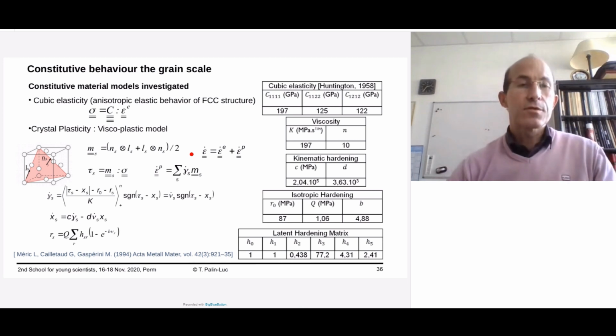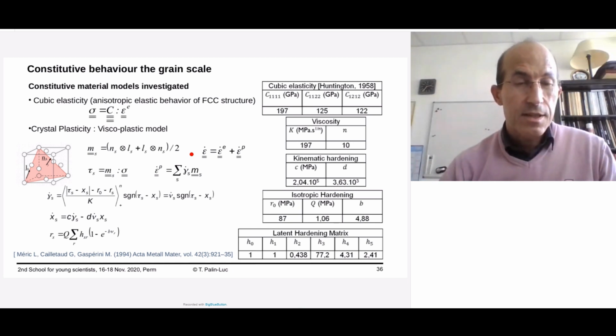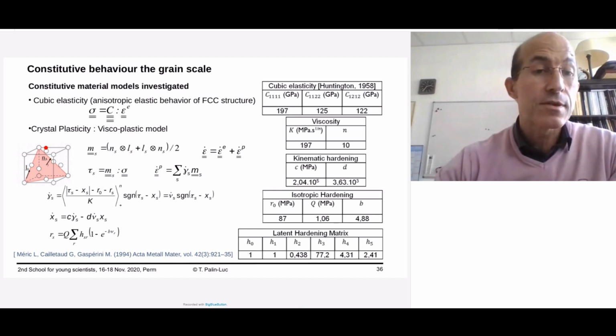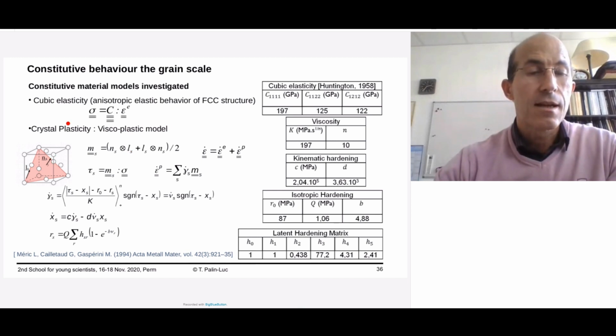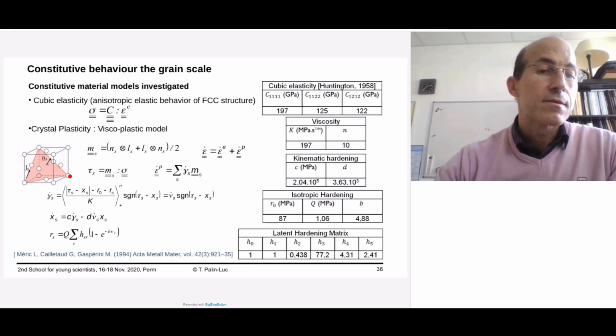The constitutive behavior of the grain in this case is given by different behaviors. There is a cubic elasticity to reproduce the anisotropic grain or crystals. And there is also a crystal plasticity behavior, which is in fact viscoplastic. This is a model written at the grain scale on the different slip systems. So a slip system is for one material plane. You can see here the crystal with a given material plane oriented by its normal. And the slip systems are on this material plane, the different directions L, where the slips can occur.